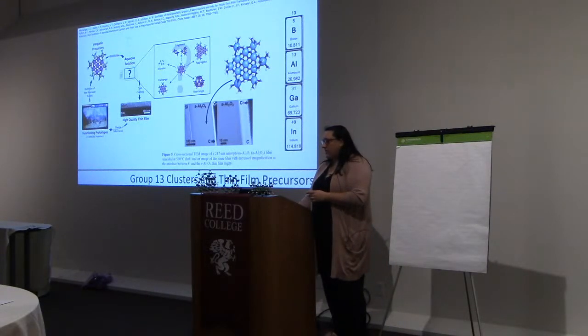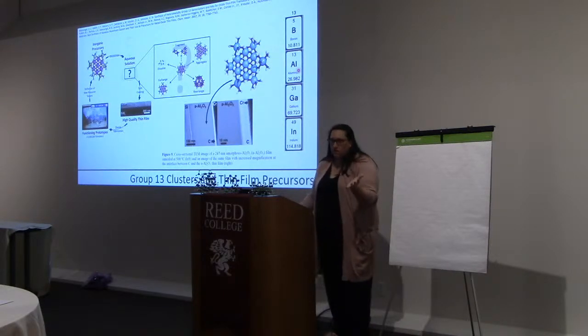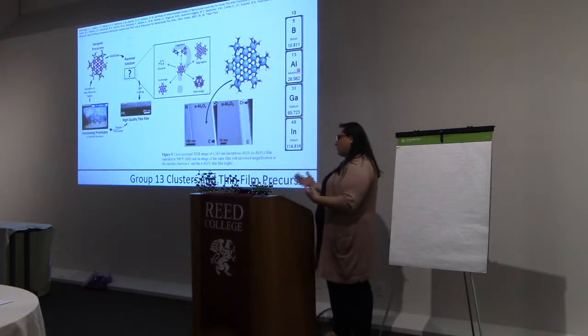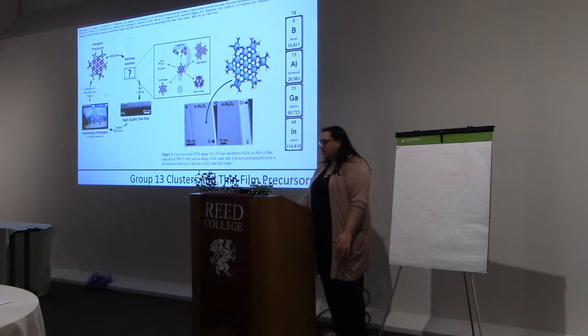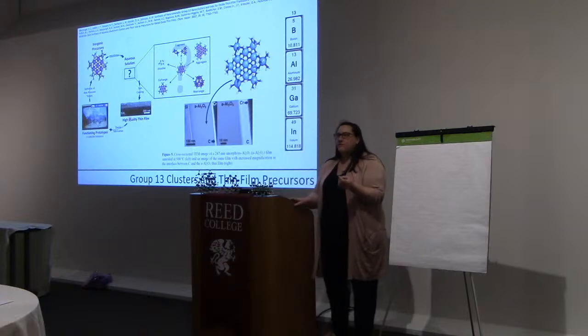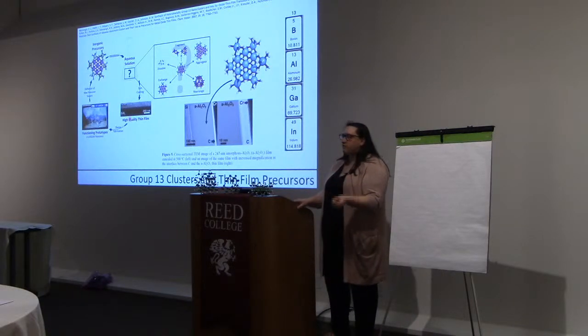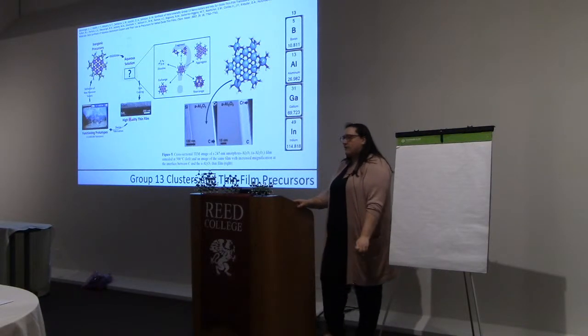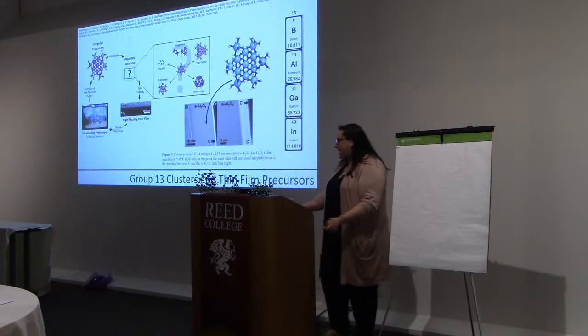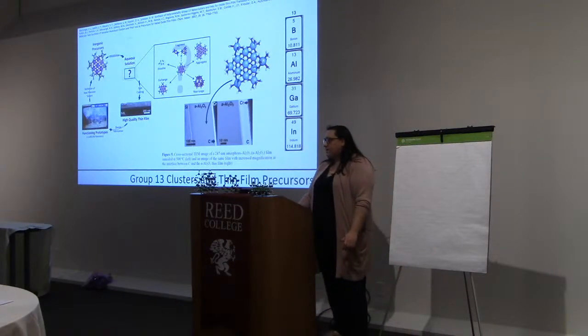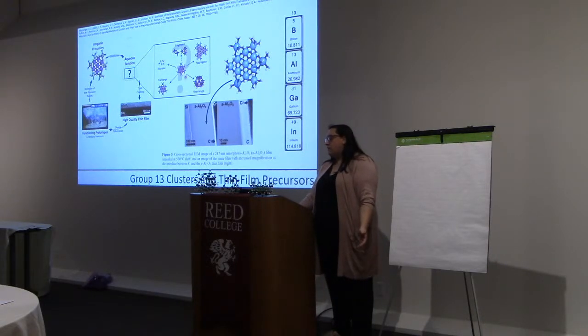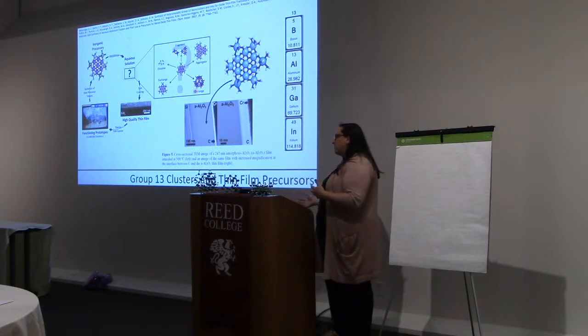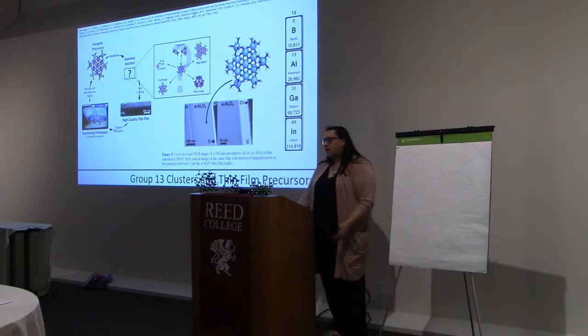Now the one I worked with in grad school was a gallium-indium cluster, and that's right below aluminum on our periodic table, so it has very similar properties. But that cluster could be turned into thin films, very dense, defect-free indium gallium oxide thin films that could be put in devices. And so in my PhD, I really looked at those solutions. They would dissolve these clusters into solution, and then the question was, well, do they just dissolve? Do they fall apart? Do they aggregate? Is there some sort of rearrangement to a different cluster in solution? And so that's what I studied.